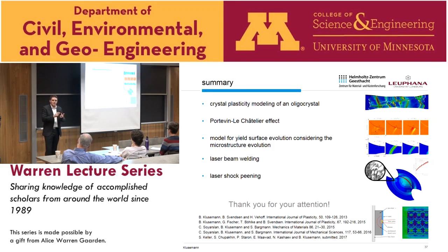This is very classically known. It has 24 glide systems, sure, it's more than a classical phenomenological model, but to account for these orientations, we also investigated what kind of glide systems you need to incorporate in BCC, because this seemed to be not obvious. We also tried 48 and we also tried 12, and all these are possible. For 24 we got the best results.